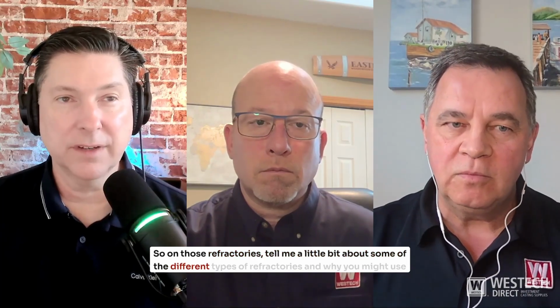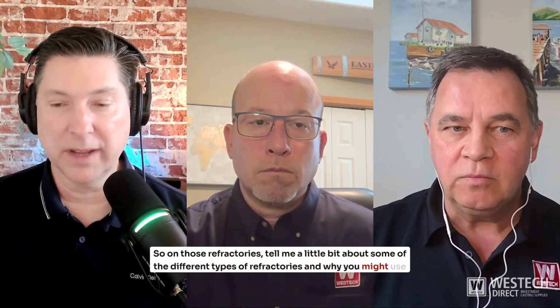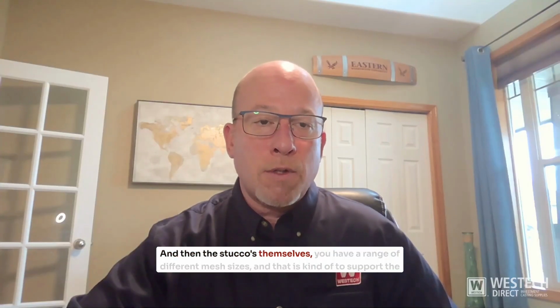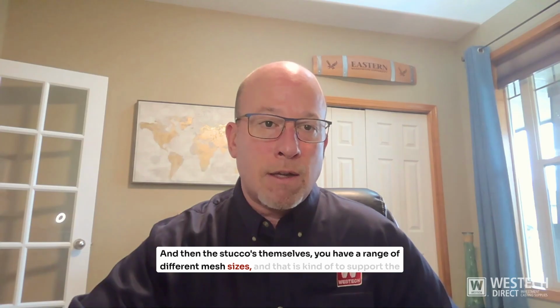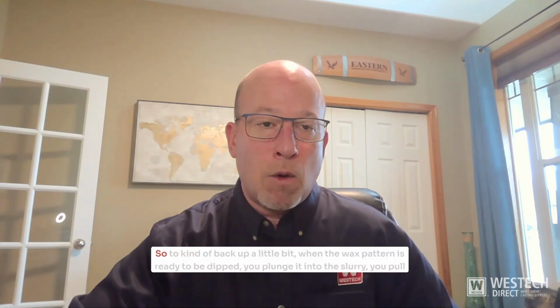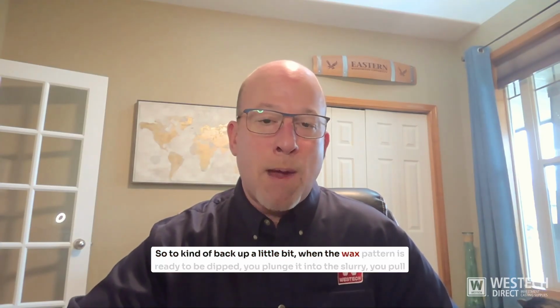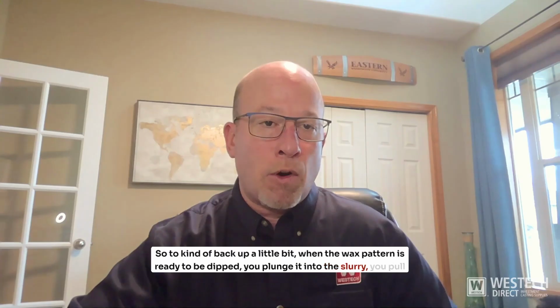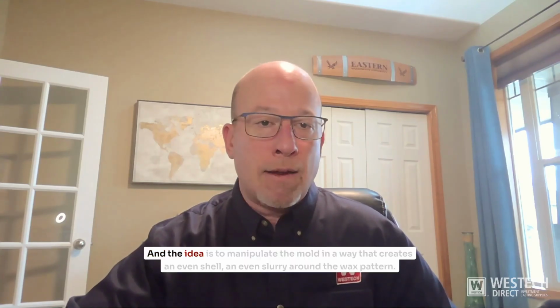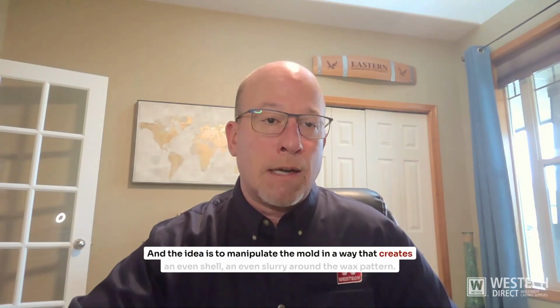So on those refractories, tell me a little bit about some of the different types of refractories and why you might use them. And Jeff, let's go to you for this question. Different refractories, you have both flour and you have stucco. Flour goes into the slurry and mixes with the binder. And then the stuccos themselves, you have a range of different mesh sizes, and that is to support the slurry once the shell has been dipped. So to back up a little bit, when the wax pattern is ready to be dipped, you plunge it into the slurry, you pull it out, and the idea is to manipulate the mold in a way that creates an even shell.